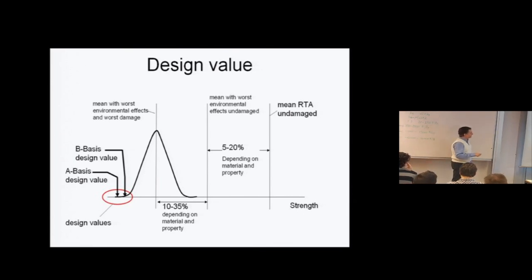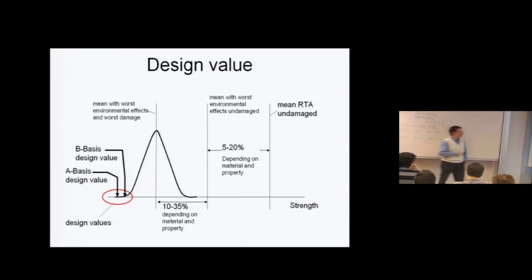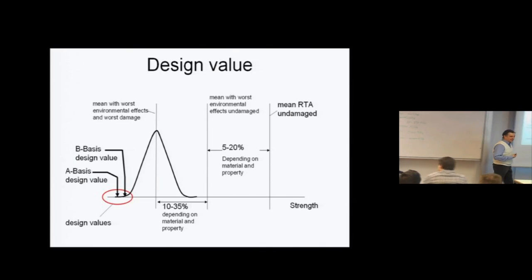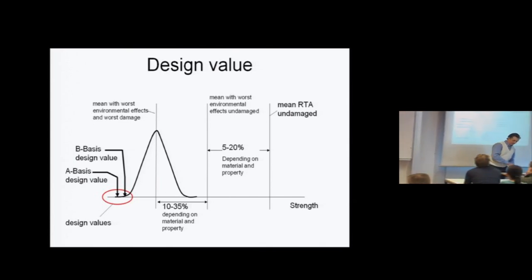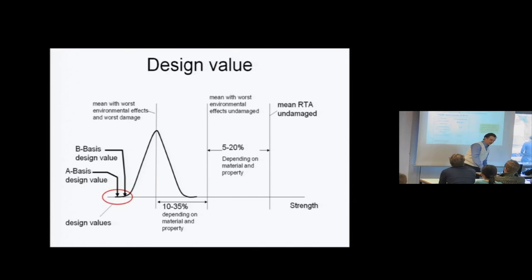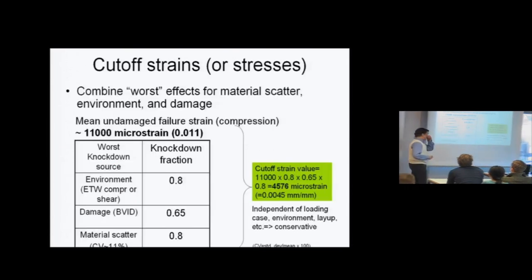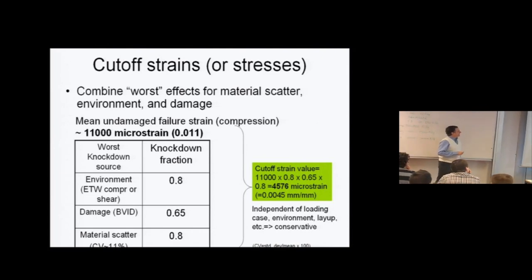And then around that, we have the distribution. We said the material scatter has a certain distribution, and we'll have to go down here to use either the B basis or the A basis design value. So from here to there, materials which compared to steel would be no contest, would be the best materials in the world, all of a sudden become comparable in some respects. And to translate this to numbers, a typical material has a mean undamaged failure strain in compression of 11,000 microstrain, or 0.011. So if I apply typical knockdowns, these are typical, so don't take them for granted, even though you will see that almost everybody uses these typical, at least for preliminary design.